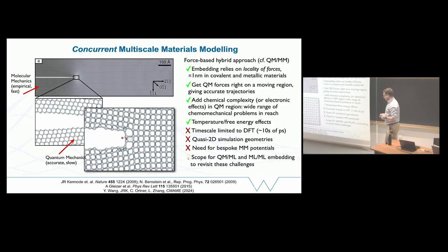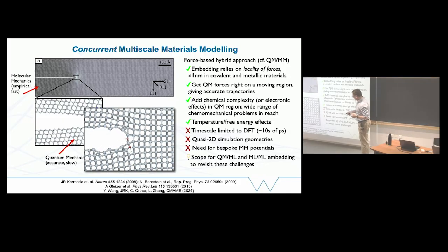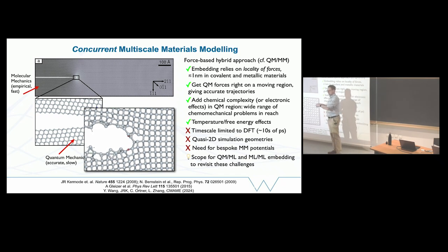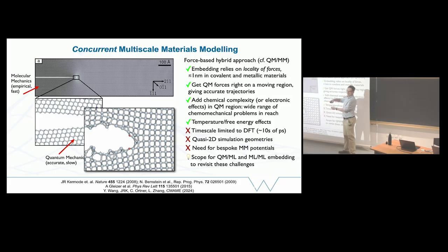We can add chemical complexity. So we can actually put in a molecule of oxygen. We can see it diffuse to a crack tip, spontaneously dissociate. It's burning one silicon-silicon bond at a load which would not be favorable for the crack to advance on its own. We're not pulling hard enough for it to be energetically favorable for the crack to move on. But if we place that oxygen there, it reacts with the strained bond at the crack tip. It dissociates, it absorbs, and we've burnt a bond and we move on by one. And that's all things that we can do within a DFT timescale. That's a reaction which itself takes place in a few picoseconds, so we can do it directly in DFT.